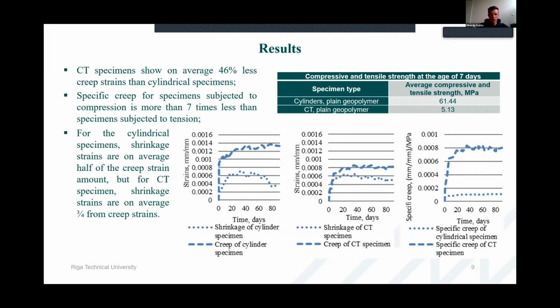So the results, as you can see on the left-hand side graph, the compression specimens show significantly higher creep strains than the compact tension specimens, approximately 46% more. But I actually have to say that because these are two different stress-strain states, it's not quite correct to evaluate the creep strains in this way.